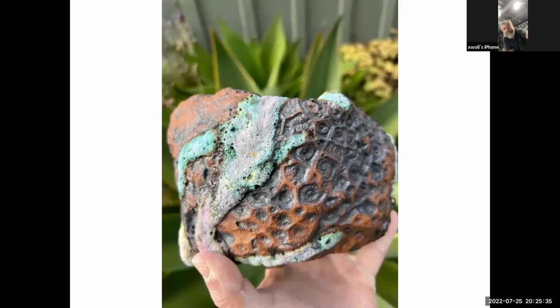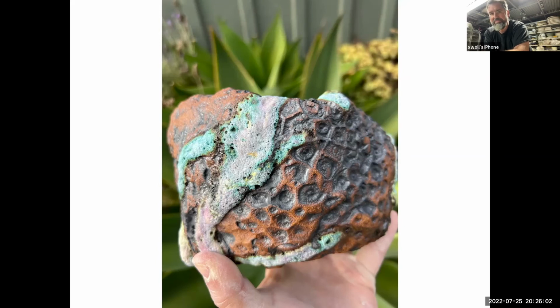Okay. So yeah, I just got these out of the kiln like 2 days ago. It's all cone 10, heavy duty reduction. This first one is basically a stamp mold that I made from a fossilized coral that I bought on eBay. So I had this idea about making these coral pots, and the glaze there is experimental. That's basically a test, and it turned out kind of cool with the different colorations. I'm adding some of that 400 mesh silicon carbide to get the glazes to foam up like that. They're reacting. There's copper glaze, and there's some other oxides that are mixing together to make that coloration.